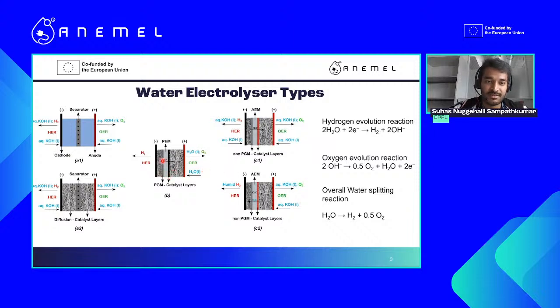But the biggest drawback is that these polymers have PFAS, basically fluorine-rich polymers. Also, they use platinum group metal catalyst, while you do not need platinum group metal catalyst in this alkaline electrolyzer format. So recently, research has developed new technology that combines the advantages of the two systems, having a polymeric membrane within an alkaline system using non-PGM electrocatalyst, which can reduce the overall cost of the system as well as toxicity, because these membranes need not have fluorine.